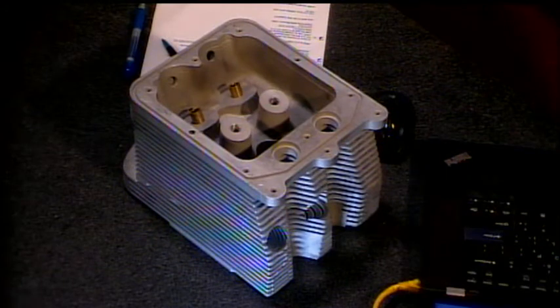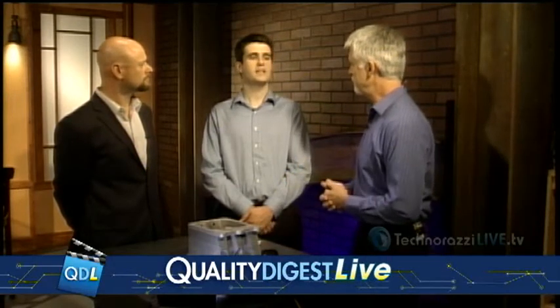So basically a person from outside the university came to you and said, 'I have this idea for an engine that's going to run on unleaded, lower octane fuel — can you figure out a way to make this?' And that's exactly what happened. We did all the design work for the casting and tooling on campus. We cast the part, did the heat treatment on the aluminum — which is cast 356 — and then sent it out for x-ray inspection, which was the only capability we didn't have on campus. When it returned, we did all the machining on the cylinder heads using our Haas CNC equipment, then quality inspection using our MicroView CMM.